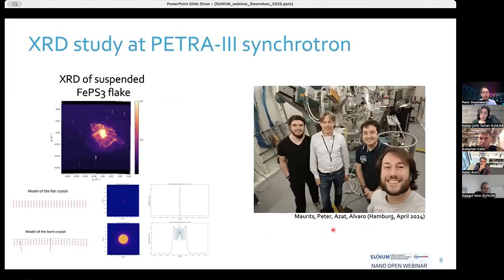We also went to a synchrotron in Hamburg, Germany, in April to also measure the lattice parameter. You see here behind us the X-ray diffractometer, and there was an X-ray source from the synchrotron by which we could also measure this lattice parameter. What we saw there is that X-ray diffraction is even harder to do on these membranes because if the membrane is a little bit bent, these diffraction peaks are broadened, and that's why you see here this kind of circular spot. So our resonance frequency measurements are a better way to study lattice parameter than these synchrotrons, was our conclusion.